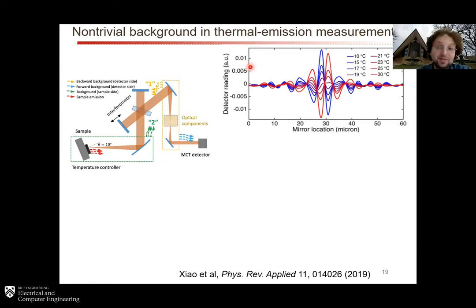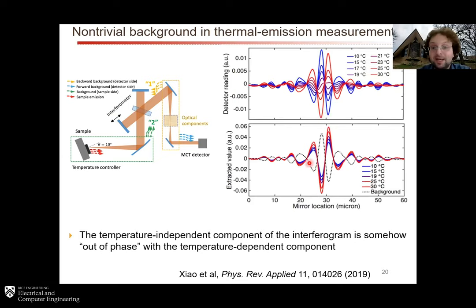An FTIR doesn't actually measure the spectrum directly. An FTIR measures a detector reading as a function of mirror location, where the mirror location is the position of this mirror in a Michelson interferometer. And so what we found is if we looked at the signal at high temperature and then at low temperature, the interferogram was actually out of phase. So every time you had a peak in the interferogram at high temperature, you had a dip in the interferogram at low temperature.